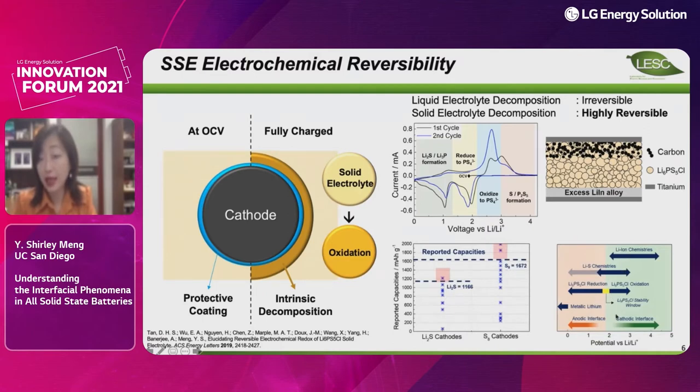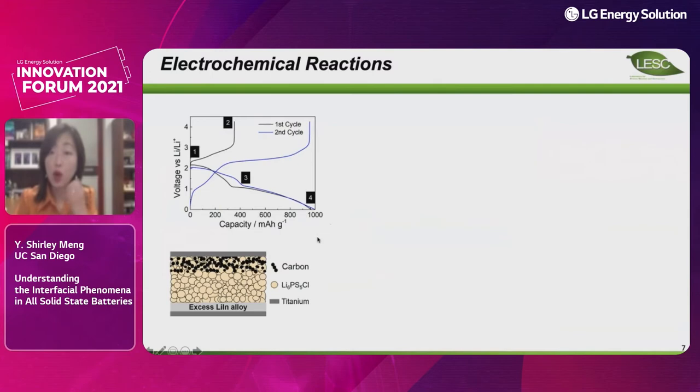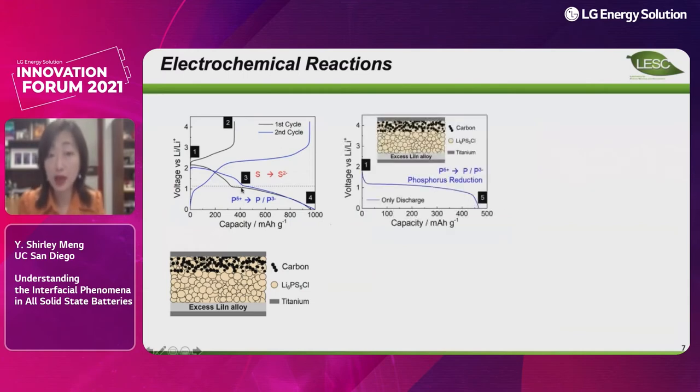When we charge NMC to higher voltages, we run into the trouble of oxidizing the solid electrolyte. NMC cathodes typically require carbon additives to enable utilization, but we can't put a lot of carbon onto cathode electrodes because that induces many side reactions. These stability issues of the solid electrolyte against NMC cathode present a big challenge. We investigated what happens during electrochemical oxidation — what products form, and whether they're good or bad for ion transport or electron transport.